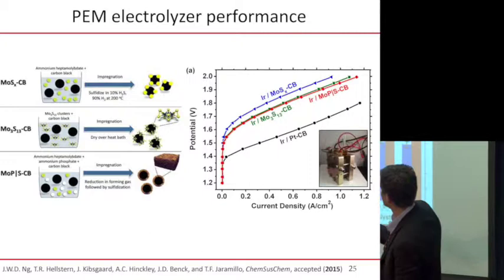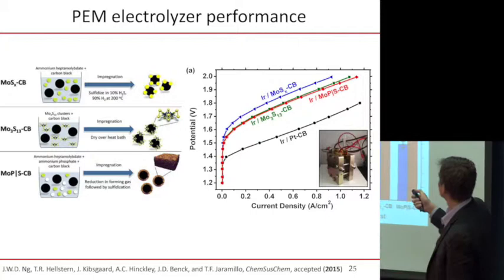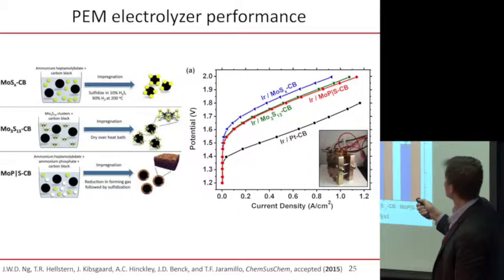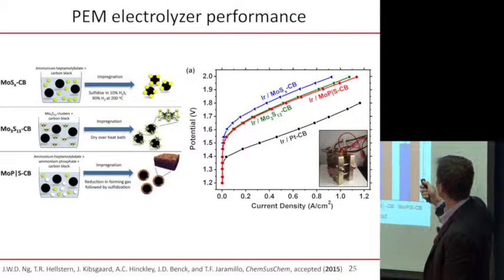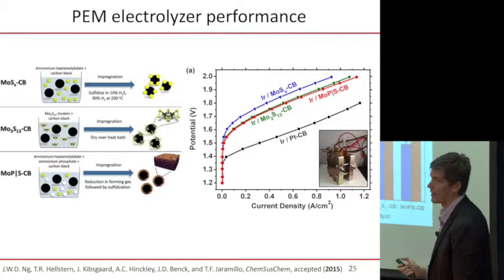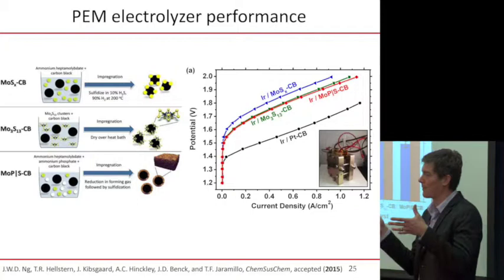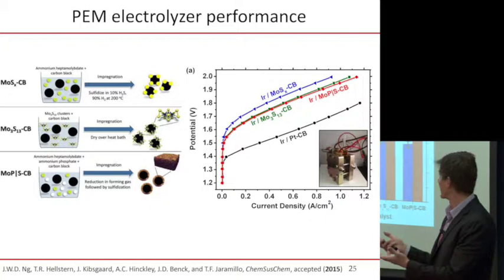Here's our voltage current plot, now inverted a little bit, where you want to get as much current out of this device as possible with a minimum amount of voltage. And what he's doing is he's showing us these different formulations of molybdenum sulfides that I was showing you earlier and how they compare versus platinum. Frankly, they're not as good as platinum, but they're pretty darn close. They're off by about 150 millivolts, maybe 200 millivolts. But remember, molybdenum sulfide is effectively a completely free and scalable abundant material versus platinum, which is not. So there's a big advantage to going to non-precious metals.